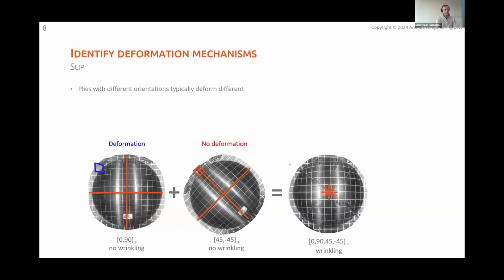So what can we say about this? Well, plies with different orientations typically deform differently. They have a rotated, in this case, deformation pattern. But it means at certain spots the deformation is hindered due to frictional interaction between the plies that is occurring there. And therefore, we can say that we need to model the friction between the plies.